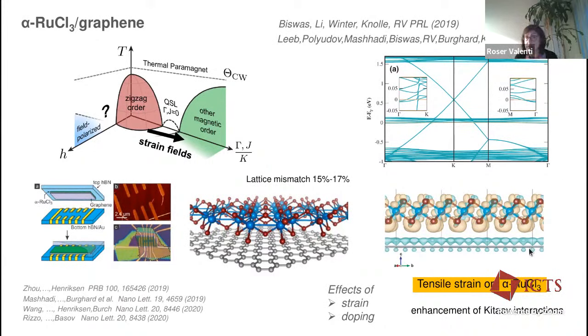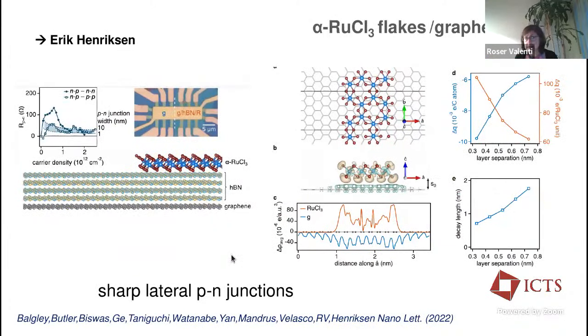This is the Fermi level now of this heterostructure, and alpha ruthenium trichloride gets electron doped. And this type of heterostructure shows an enhancement of Kitaev interactions. Now, one can even use these heterostructures for more application purposes. And this is what Eric Henriksen has been recently doing, where in fact he showed that you can create very sharp lateral p-n junctions. These are our calculations, where one sees that the charge transfer changes very sharply at the edges, and this can be used for technological purposes.